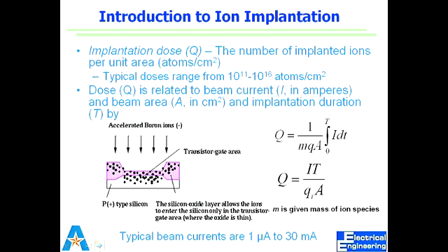So if you draw a relationship, that would be integrating that beam for the time it takes. Charge is constant, area is constant, m is a factor which is the mass of the ionic species. So these are constant. So what matters is how long we bombard that beam on a surface, right? So a closed form is simply I T over Q A. Q is the total charge.